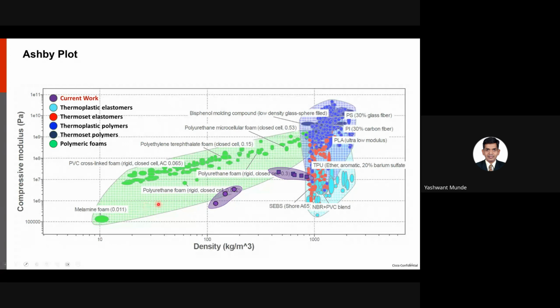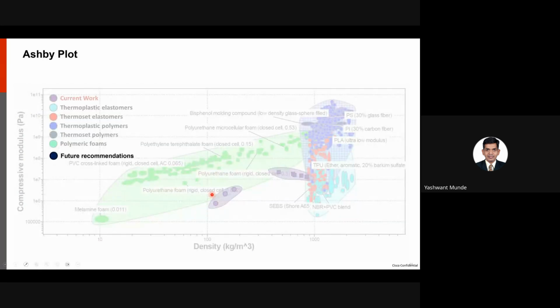And here we see some polyurethane rigid foams, PVC cross-linked foams, and here are our foams at this stage. These are some epoxy-based, very stiff foams, so we will not compare them here. Right now we have the strength slightly lower, but in a reasonable density range. But by increasing the inherent hard to soft segment ratio, which we did not change in this case, we can push this up in terms of the modulus, and then architecting them, which would create some hollow regions, would reduce this density, but also reduce the compressive modulus a little bit.